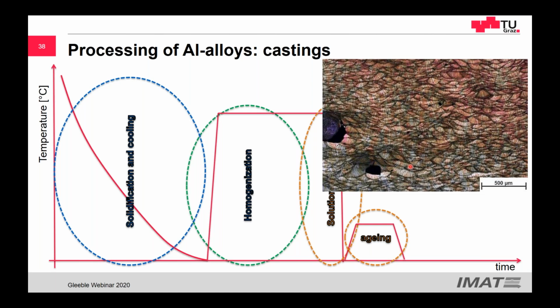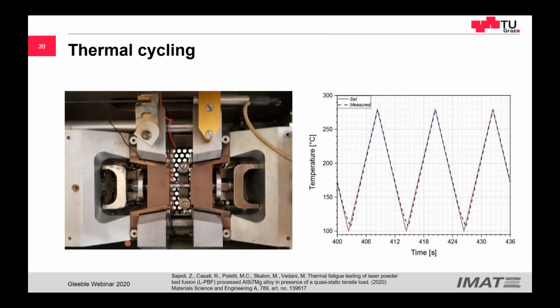And we took this material and we tested what may happen in service. So during service, we have thermal cycling. We accelerate this. We did it on the Gleeble, this thermal cycling under a given load. We also wanted to do thermal cycling combined with loads. This is possible, but the interpretation of the data was too difficult. So what we did is we took the sample, put the thermocouple on it, and we went into thermal cycling. So the temperature that we set can be seen here.